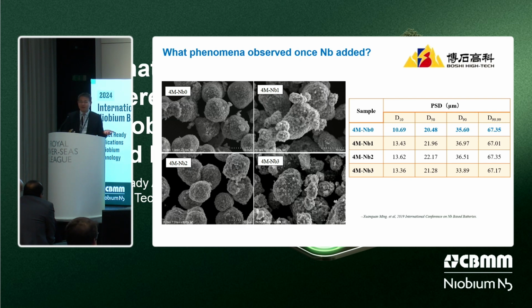Maybe some professor will show some data in NCM. Niobium will refine the primary particle size. What's the reason? It's very interesting. But here, once we increase the primary particle size, you can increase the compacted density. Of course, in NCM, if you refine the primary particle size, you can increase the mechanical performance of the particle. It also could increase the rolling pressure and also can improve the tap density or something.